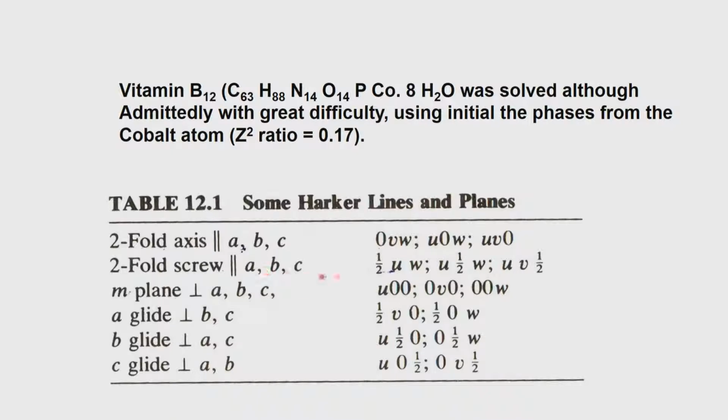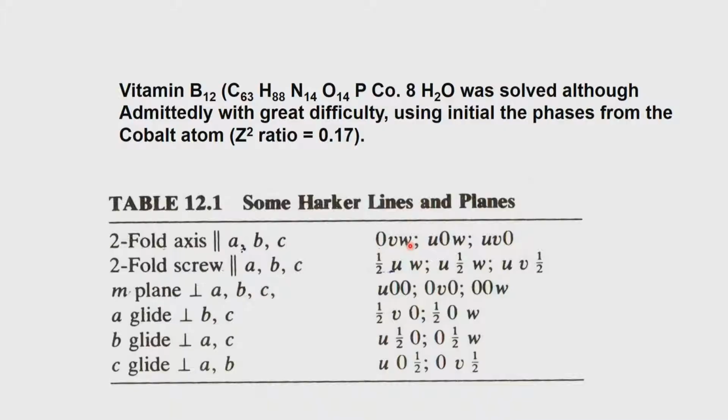So, I have given only the two-fold example here to keep it simple. If we now have this system P222, we look at these three projections and we get solutions for UV, VW, and UW. If the system is P222, then there are two-fold axes perpendicular to each other, just as an example. Then we have the solution for V and W for the heavy atom position, for U and W for the heavy atom position, and for U and V for the heavy atom position.